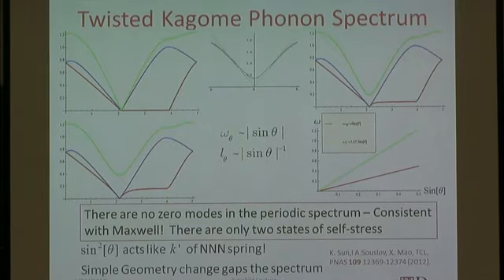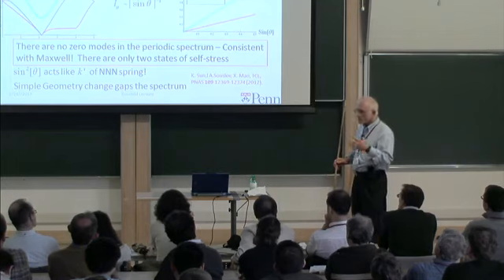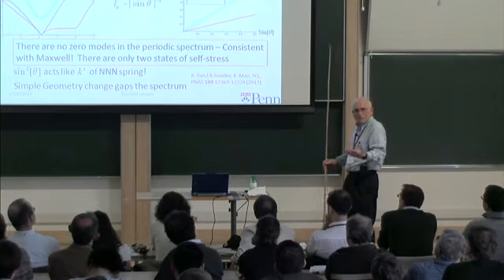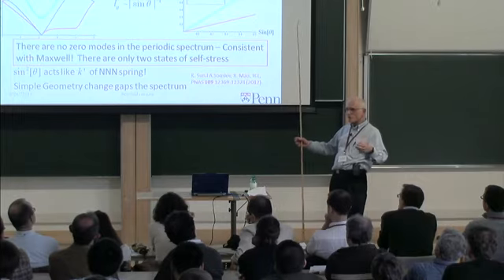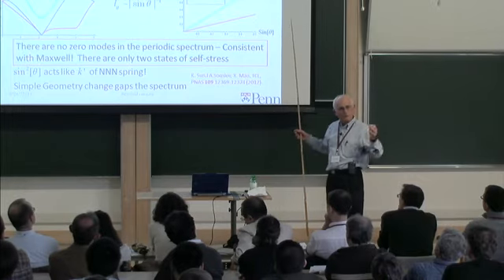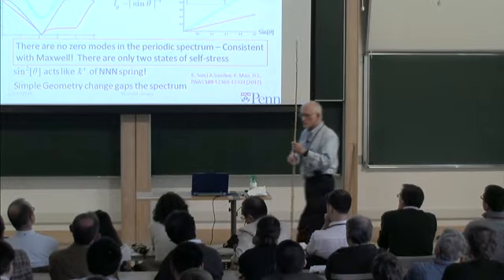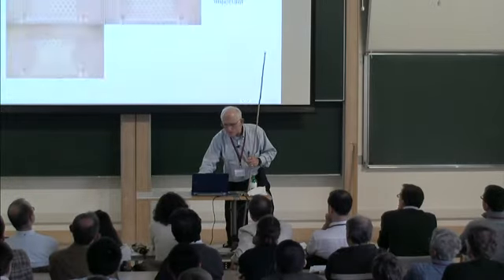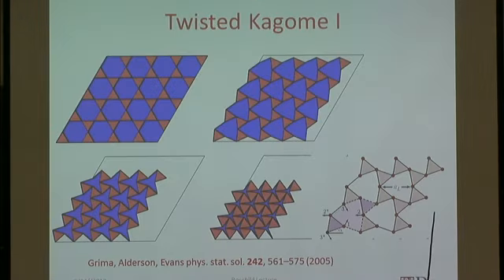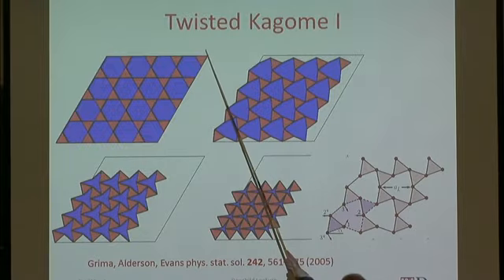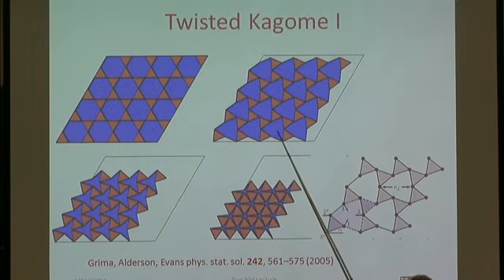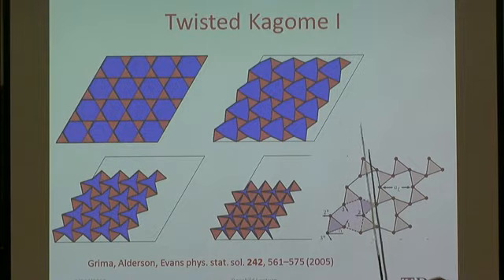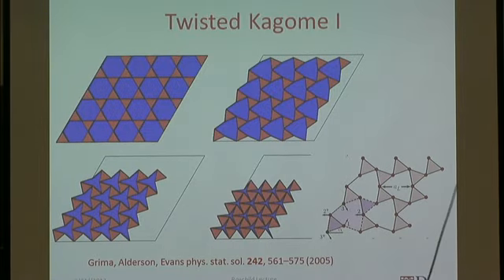So twisting has an effect which is very similar to adding next nearest neighbor forces, and it doesn't violate Maxwell, because remember, Maxwell said that we have a periodic structure, we should have no zero modes. So what's happened is we've lost all of the states of self-stress, and it's pretty clear that we've lost the states of self-stress because this lattice supports stresses for each of the straight lines. This lattice doesn't have any straight lines, and the only states of self-stress are two trivial ones which involve the whole sample.